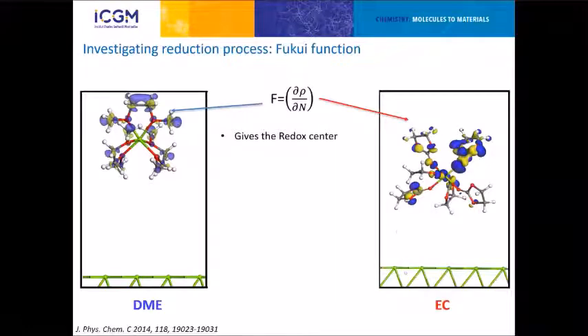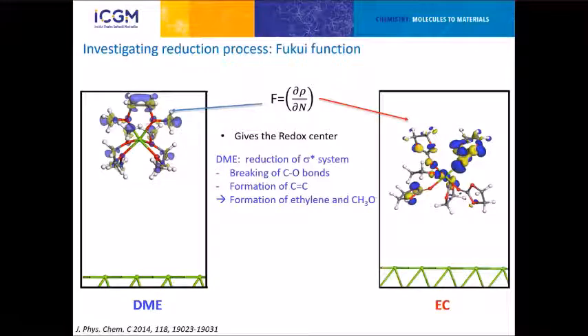To really understand, we need to focus on where the reduction occurs. This can be given by the Fukui function. The Fukui function is a mathematical tool that gives you the chemical identity of the reduction center. When we compute it, it shows where the electron flows from the electrode. So when I just add an electron to this molecule, I directly see that in the DME case, I'm getting a sigma star reduction that will lead to C-O bond breaking and the formation, you see it there, of a C double bond, which tells you that we're going toward the formation of ethylene and methanol.